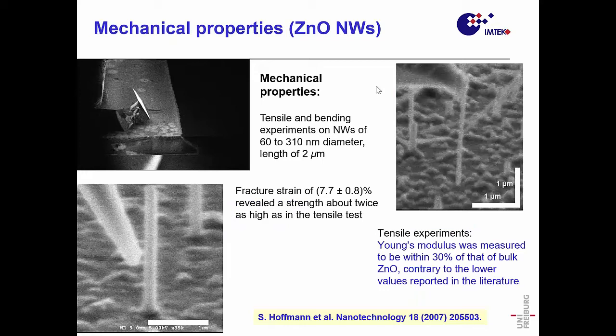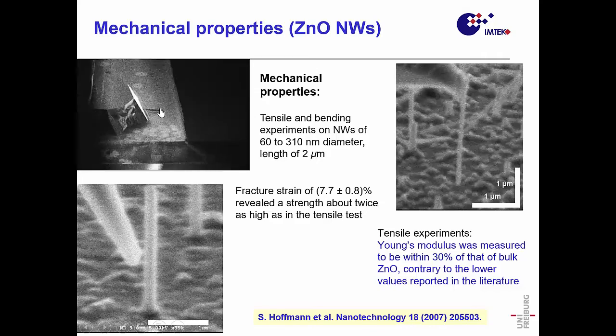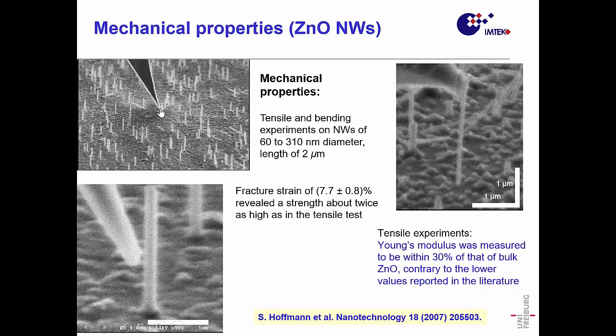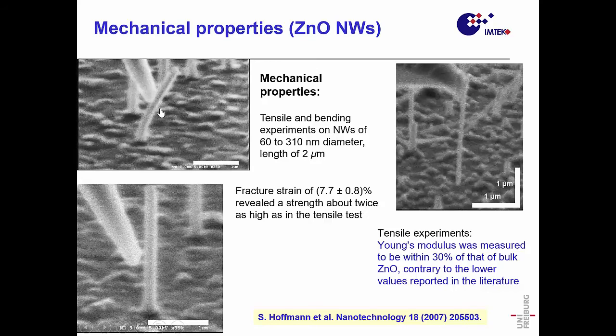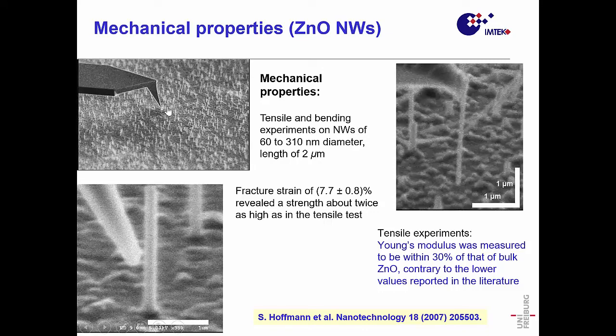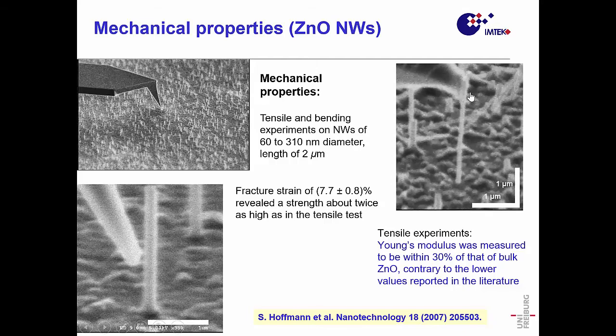So let's go from what we have here, thinking about the mechanical properties. I think that's rather an interesting thing, because you might ask yourself, how mechanically stable are these nanowires? To test that, you can take single nanowires. These were grown randomly, so we didn't pay attention in this experiment. We just wanted to have them spread over a large area at a distance. To give you an idea, we have a tip inside an SEM, and then you kind of break them. If you approach the nanowire with the tip and give it a short pulse, then the nanowire is kind of glued to the tip. And what you can do then is that.